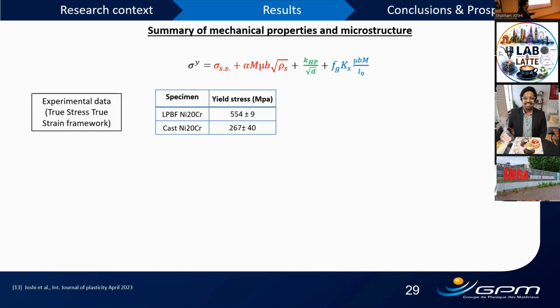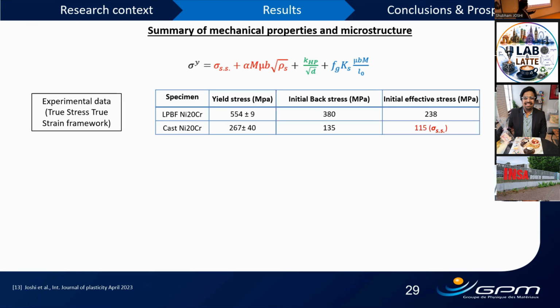So the highlight of this PhD, the message I want to give on this slide, is that we can look at the several parameters seen in this equation, but the work of my PhD was to explain that extracting these parameters from experiments or literature is not hard, and we can actually do it via simple experiments. For example, yield stress, which is required in modeling, can be easily extracted from mechanical loading. Initial back stress and initial effective stress can be computed from the loading, relaxation, unloading test. And this initial effective stress for the cast has been used as the solid solution, because we believe at effective stress there is no initial dislocation density, or the influence of initial dislocation density is quite low. So that means only the solid solution should logically contribute.